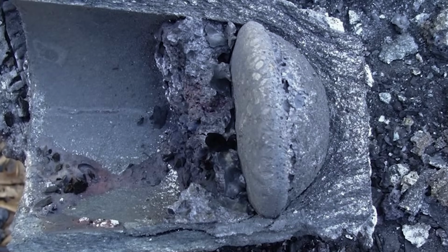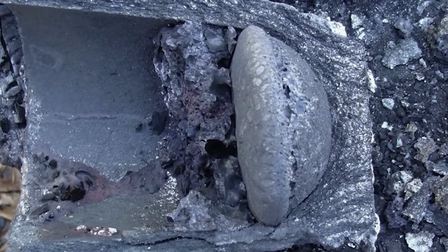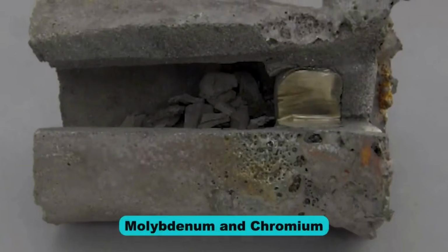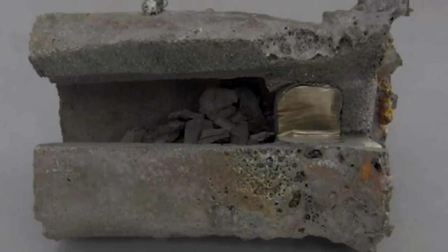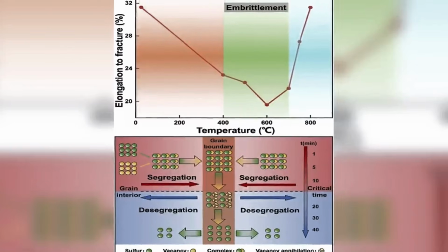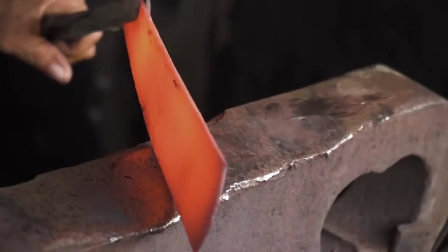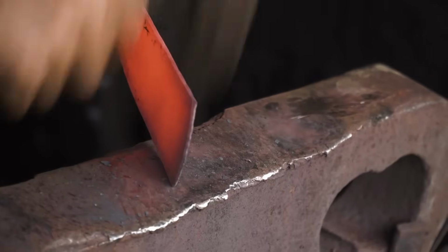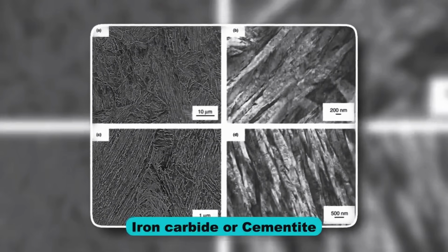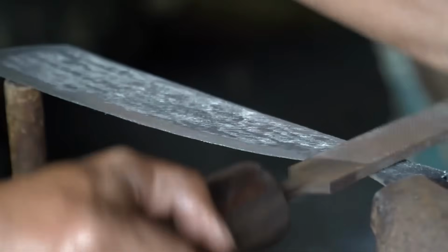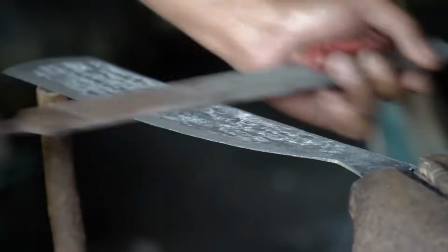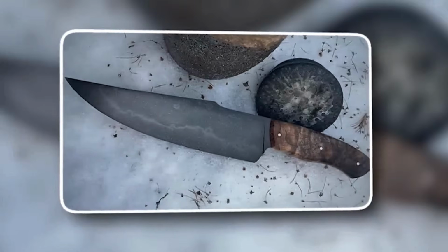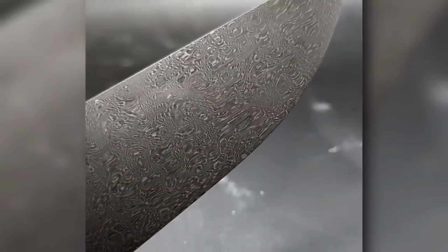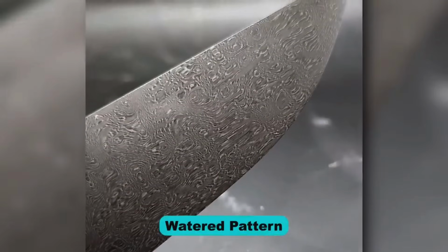Here's what it did. When the Wootz ingot cooled after smelting, the vanadium atoms, along with other trace elements like molybdenum and chromium, were pushed out of the solidifying iron crystals. They accumulated along the boundaries between crystal grains, forming thin sheets running through the steel. When the ingot was later heated and hammered into a blade, these impurity-rich zones acted as nucleation sites, places where an extremely hard compound called iron carbide or cementite clustered preferentially. The result was alternating bands of carbide-rich and carbide-poor steel running through the blade. The hard bands gave it its edge. The softer bands gave it flexibility. And when the surface was etched, those bands produced the famous watered pattern.